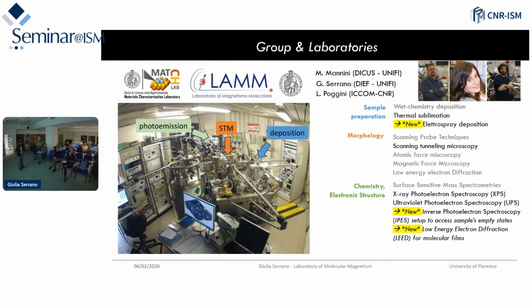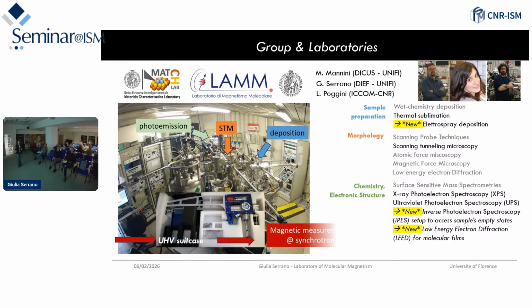performing molecular deposition by thermal sublimation, but we also implemented an electrospray deposition method for fragile molecular structures, a scanning tunneling microscope working in a helium flow, so capable of going down to 40K more or less, and the photoemission spectroscopy part with XPS, UPS, and now we recently bought an inverse photoelectron spectroscopy and also a low-energy electron diffraction suited properly for molecular systems, which are quite new, so we still haven't used them so much.